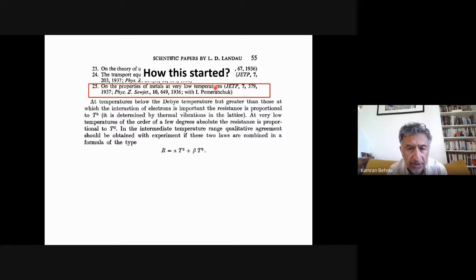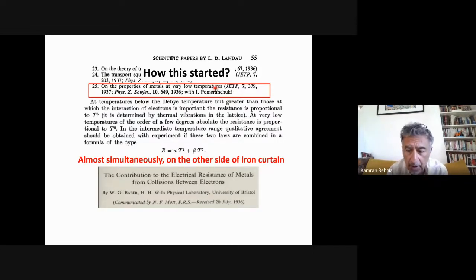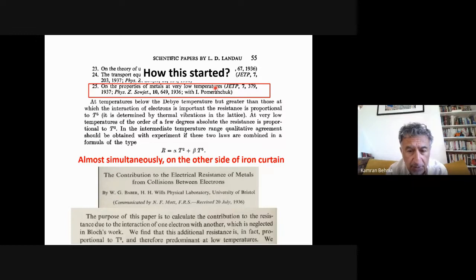He proposed this idea that, yes, resistivity should have a T squared and a T5 term. The T squared term comes from the fact that electrons collide with each other. Almost simultaneously, in England, there was this paper by Baber, where he also proposed that electron-electron scattering should give rise to a T squared term. Note that at that time, T squared resistivity was rarely observed. So this is really a kind of theoretical prediction, which was confirmed afterwards by experiments.